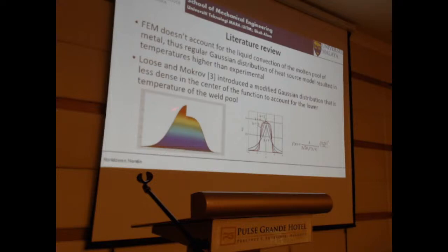If you can see on the left, there is a flattening at the top, and it's a bit fatter, a bit wider. Okay, so that is to account for the discrepancy between simulation and experiment, where if you've done early simulation, you will find that usually you get a peak temperature that is not realistic. Okay, so what he does is introduce this lambda exponent. So if you increase the exponent, you will see that the peak is flattened.